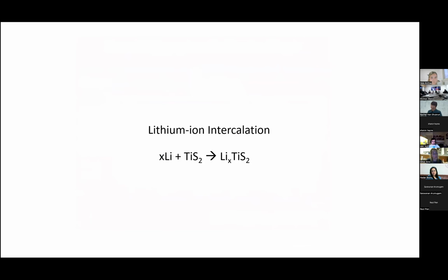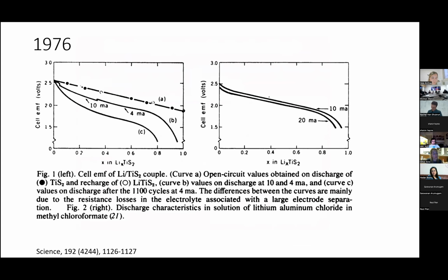So the first lithium ion intercalation phenomenon was explained using titanium sulfide cathode material. This is the first paper that Stanley Whittingham published in Science in the year 1976. This is the only figure in the paper. The curve A in figure 1 shows the open circuit voltage of the cell at different percentages of lithium in titanium sulfide, and curve B shows the discharge curve, meaning when the lithium is getting back inside that metal sulfide. So how is the percentage of lithium coming back? It is the amount of lithium that can be converted into lithium atoms corresponding to the number of electrons that we are drawing, for example at 10 milliamps. So this is B.